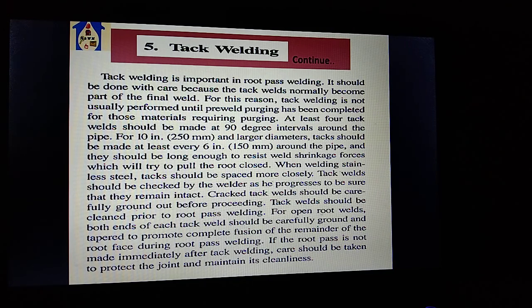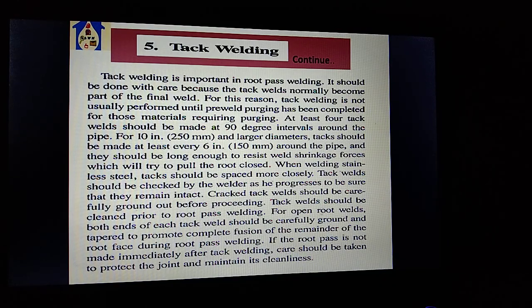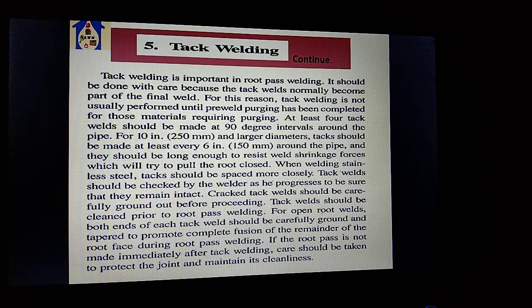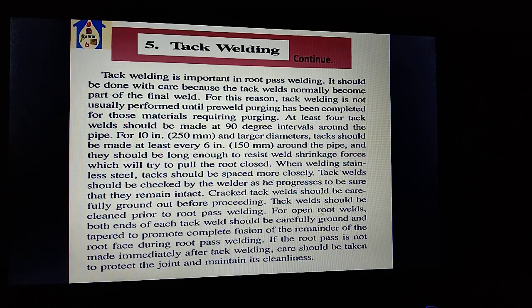For open root welds, both ends of each tack weld should be carefully ground and tapered to promote complete fusion of the root face. During root pass welding, if the root pass welding is not made immediately after the tack weld, care should be taken to protect the joint and maintain cleanliness.